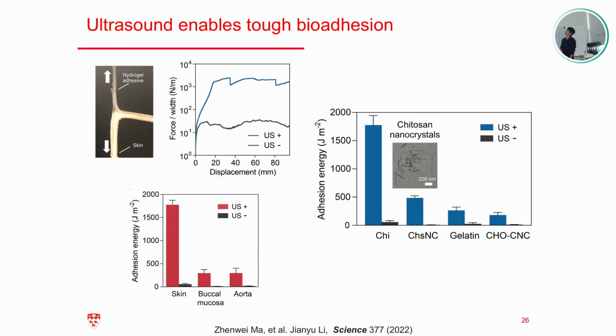So here is the quick result showing the effectiveness of this strategy. We want to form adhesion between the hydrogel and the pig skin. Without ultrasound, we got a very low level of adhesion energy. That is the T-peeling test. You can see the adhesion energy for this case would be around 30 or something for the case without ultrasound. Even though you use an adhesive polymer in between, it cannot get over the skin barrier. With the help of ultrasound, we can dramatically enhance the adhesion by around 2 orders of magnitude, so over 1,000 joules per square meter.